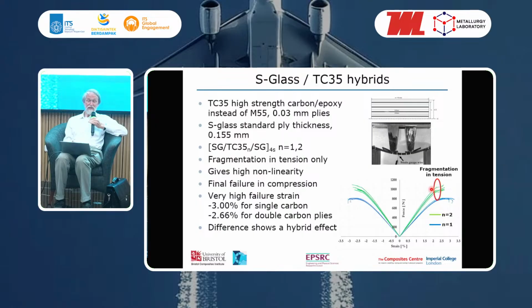We see in both cases this fragmentation in tension, but there's a noticeable difference in the final failure strain. And in fact, the final failure occurs in compression. So it fragments in tension, and then we get a failure in compression, and the strain actually is different in the 2 cases. So for the single carbon fibre, it goes up to 3%, which is a very high strain for a carbon fibre composite. 3% strain at which we get catastrophic failure, but only 2.6% when we have a double carbon fibre. So this is showing a sort of hybrid effect.